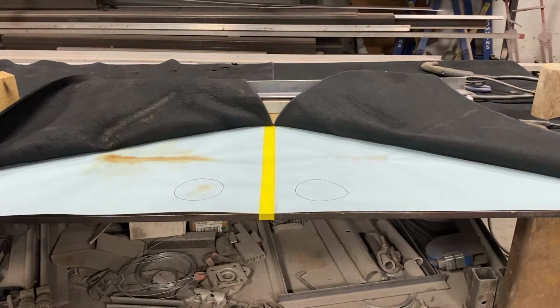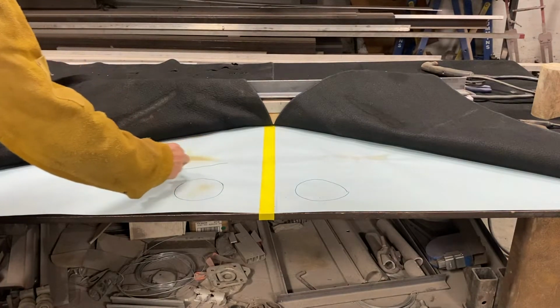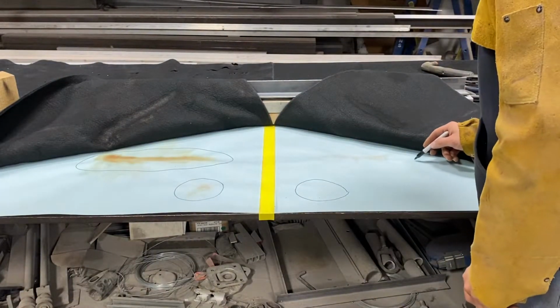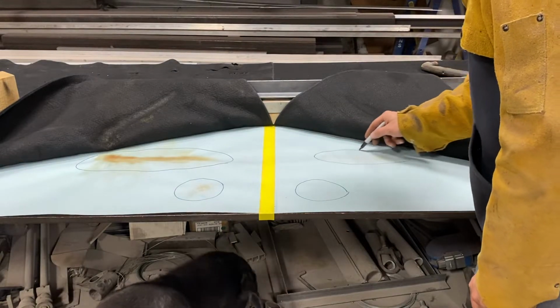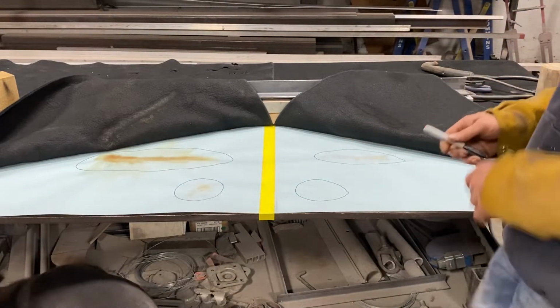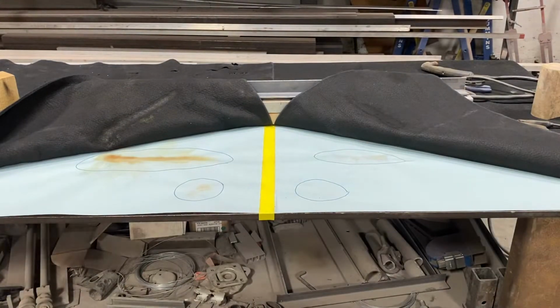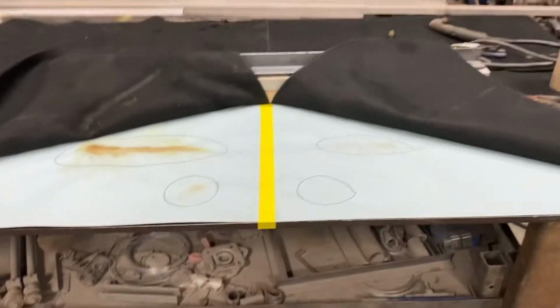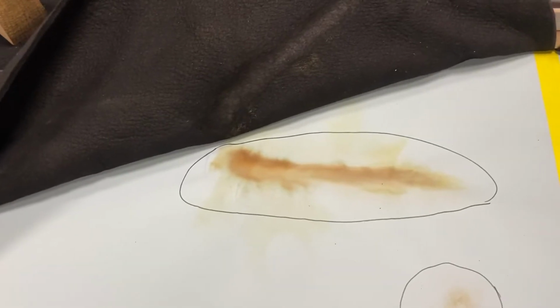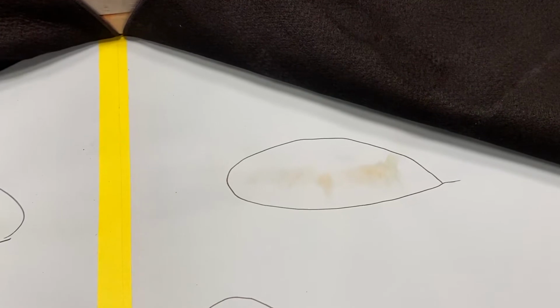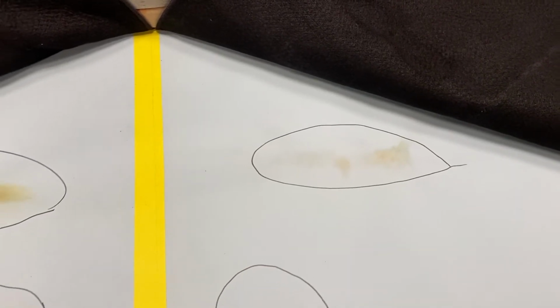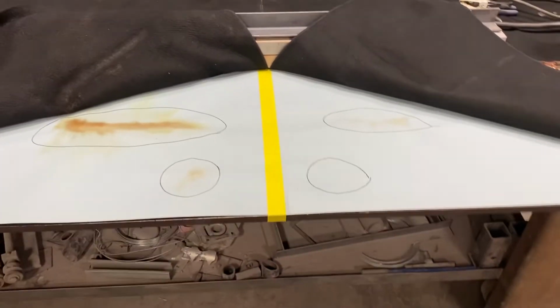So right there you can see that the standard one doesn't hold up good at all. I mean, we got some major burn through. Over here on the 3-layer, I mean, we got some burn through, but it's not crazy. So on the standard one, I'll get you a closer look. I mean, it's definitely burnt through. On the 3-layer one, it did pretty darn good, especially for as close as we had that darn torch.